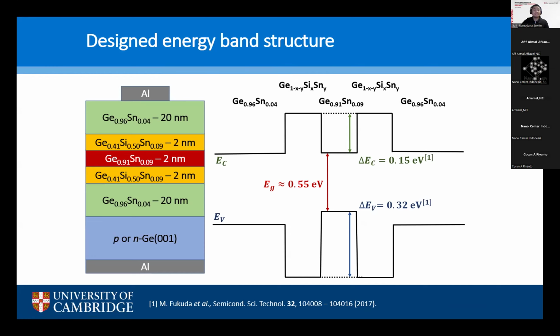So basically, essentially, we wanted to have a sufficiently large valence band offset so that we hope to be able to get at least the first resonance state to occur. Because if it's too small, then quantum confinement does not occur, because basically you need a larger band offset to capture the first ground state level.